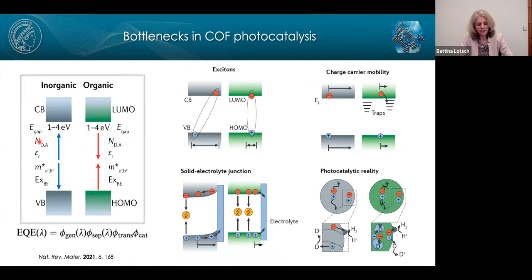However, things get different when we look at other factors like charge carrier concentration, dielectric constants, effective hole and electron masses, and also exciton binding energies. Just to give you an idea, in inorganic systems, excitons are often Wannier-Mott type excitons that are rather loosely bound and can easily be separated. This is very different in organic systems, where we typically have strongly bound excitons, Frenkel type excitons, that are very difficult to separate simply because they have high exciton binding energies.